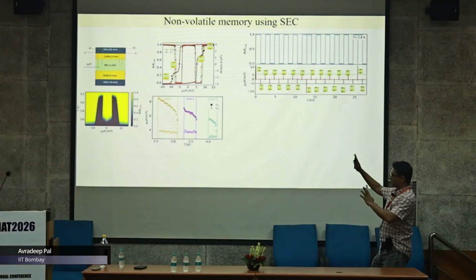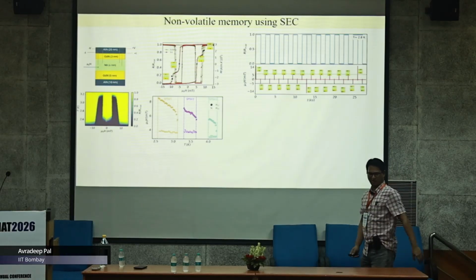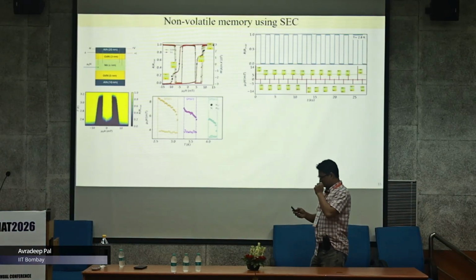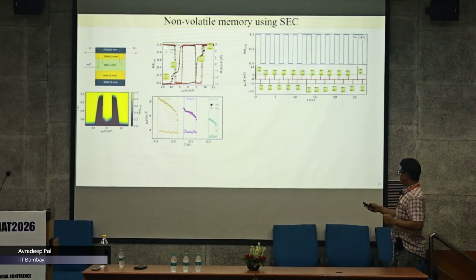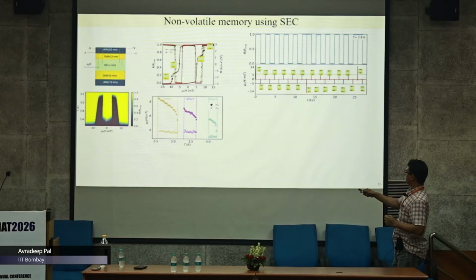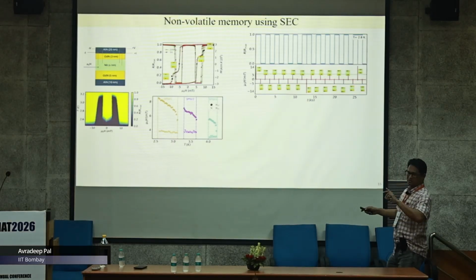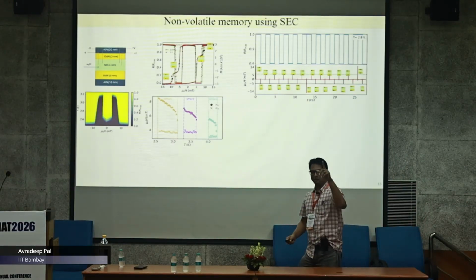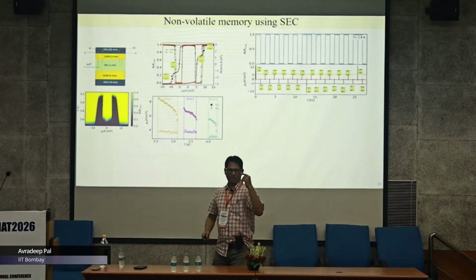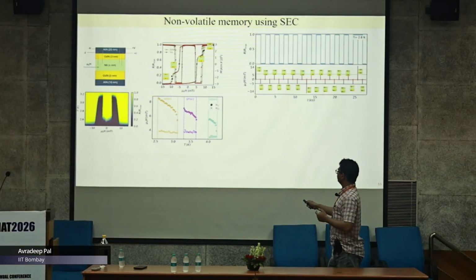And we have done many thousands of cycles. I'm showing you just a snapshot over here. The interesting thing really over here is that when I'm doing this cycling, I'm basically switching between this field and this field, okay? So I'm going around in the minor loop of the hard ferromagnet. I'm doing the full loop of the soft ferromagnet.